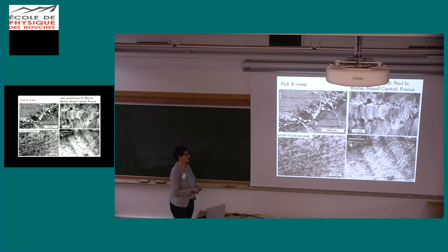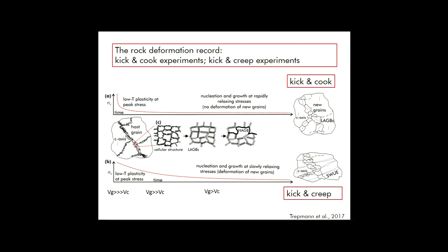So if you tilt it a little bit, then here the dislocations will pop up and here the dislocations will disappear. So there is a high dislocation density also within this rock here, so within the host crystal. Obviously during creep we not only localize the deformation in the highly damaged zones, but we also have some deformation in the host rock. But then within the areas of high dislocation density introduced during the kick, we see the major recrystallization going on. So we summarize that.